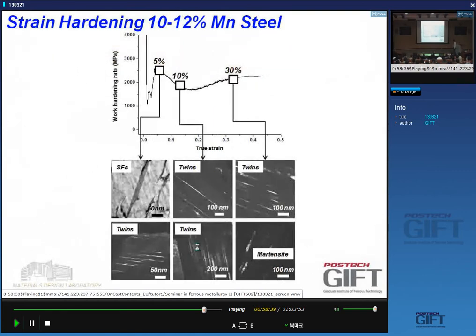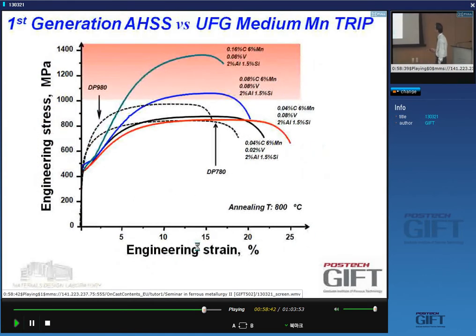All right. So, the properties, it's nice now when I conclude to have a look at how they compare with industry standards today. Today, a good standard material of a high strength material is what we call a first generation advanced high strength steel. It's our DP steels, DP780 and DP980. These are very important materials today in automotive construction. And overlaid on this, you see the stress strain curve of some of these intermediate and medium manganese steels.